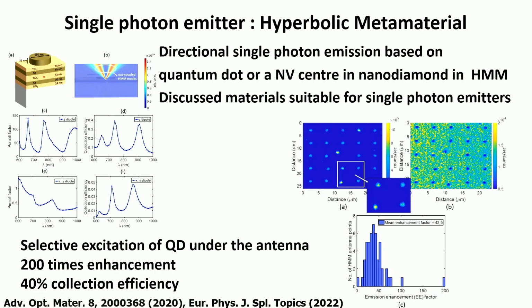Right. So we made such structures based on titanium dioxide and silver or gold. And with a patch antenna on top and a single nanoparticle, it can be either a colloidal quantum dot or a nanodiamond with a single defect inside. So the patch antenna is designed so that the numerical aperture matches with the available objective. So we have freedom to design our structure for the existing optical setup. So we showed about 200 times enhancement in the emission and 40% collection efficiency in these structures.